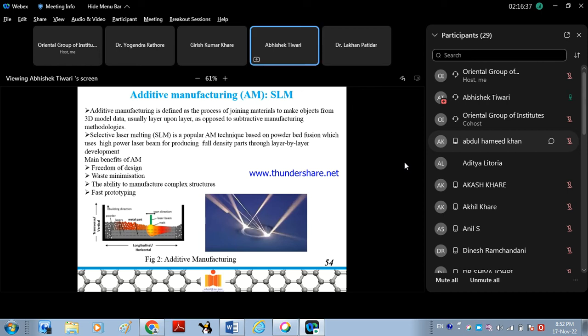One of the very good advantages of SLM is that it can produce really dense parts compared to other processing methods like direct energy deposition and wire arc deposition. The quality is very good. The only limitation is that the components we can create are small in size. You can create a component like 10 centimeter by 10 centimeter by 10 centimeter, but beyond that it is going to be difficult.